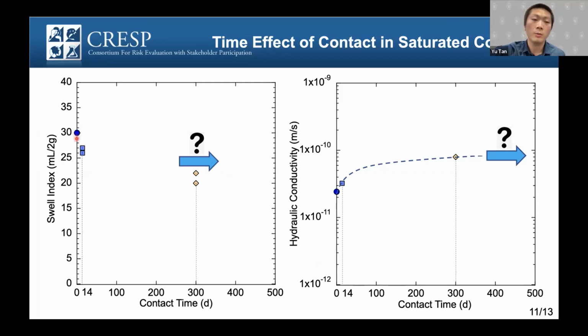GCL. Comparing to the fresh GCL, after 14 days reaction the swell index decreased a little bit. And after reacting for 300 days, the swell index decreased a little bit more. This is consistent with our hydraulic conductivity result. After 14 days interaction, the hydraulic conductivity increased a little bit compared to the fresh GCL, and increased a little bit more after 300 days interaction.